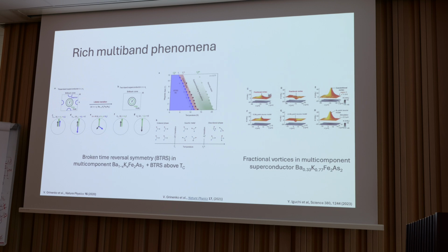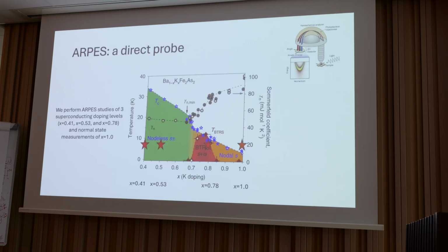So then to get a better understanding of that, or attempt to get a better understanding of that, I should say, we can use ARPES, which is able to directly probe these different bands. So with that in mind, we performed ARPES studies of 3 superconducting hole doping levels, one of 41%, which is right around optimal doping, one of 53%, which is above optimal doping but below the Lifshitz transition, and one of 78%, which is above the Lifshitz transition and technically in this broken time reversal symmetry regime.